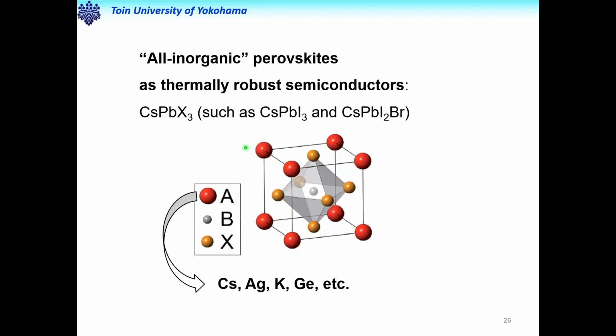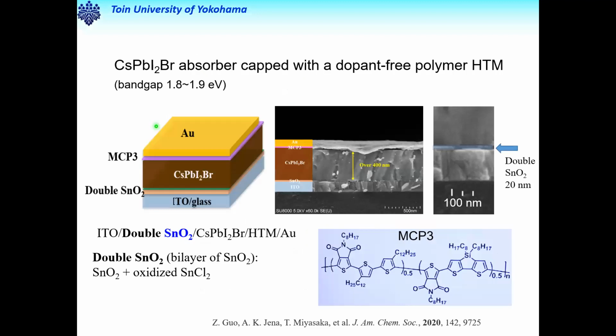But the next stage is to make the all-inorganic perovskite. In other words, the organic-element-free perovskite, to ensure high thermal stability, hopefully up to beyond 200 degrees Celsius. So our choice was cesium lead halide, this composition, where cesium replaces the organic methylammonium or formamidinium cation. As a partner, the hole transport material is also solution processable. We chose a copolymer material as the hole transport material. This also has relatively high thermal stability.